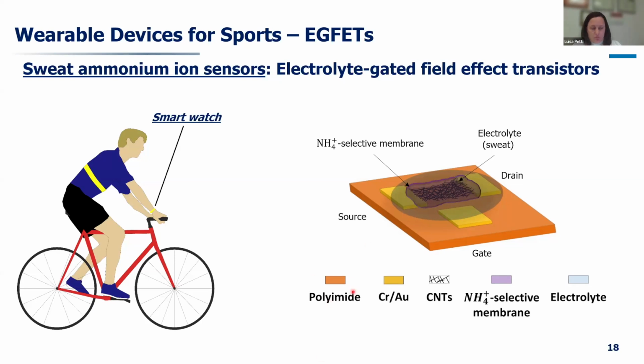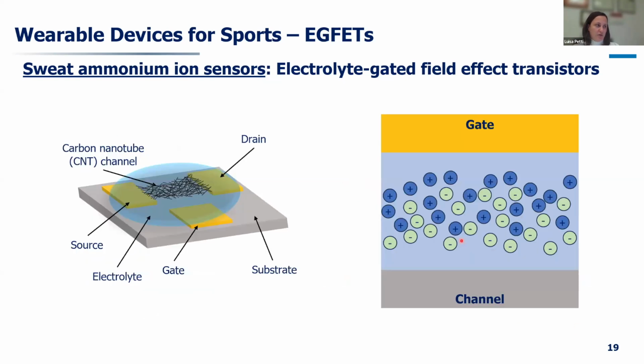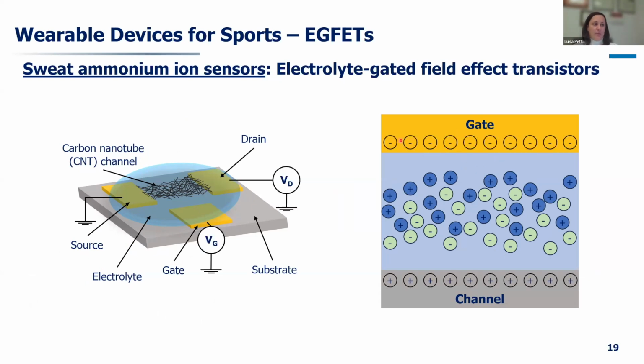What you see, so the device has a polyimide, chromium gold source and drain, the carbon nanotubes, and then the electrolyte. This is the structure again. How does that work? If we apply a negative gate, because in this case the random network of carbon nanotubes is actually behaving as a p-type semiconductor.